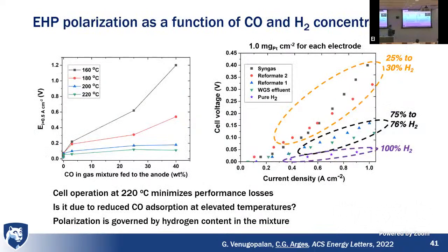So what was sort of interesting is that we said, okay, at the higher temperature, the platinum can tolerate this carbon monoxide, which is this catalyst poison, better. So if we look at the carbon monoxide content in different gas feeds at different temperatures, we see here at 220, it didn't matter if we had 40% in a gas feed or 20 ppm. So it seemed, that idea, that hypothesis, right, that higher temperature is paramount to tolerating large CO content.